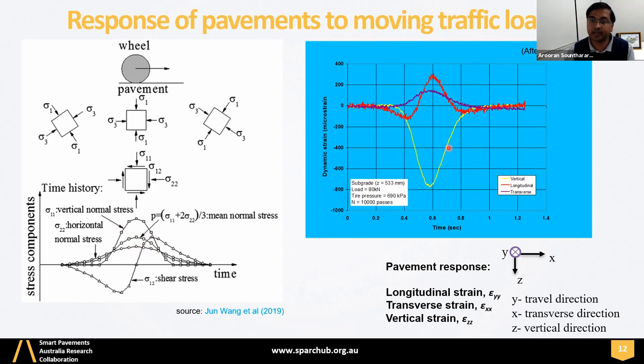This is a real measurement in the field when the vehicle moves. So you see the time here. The vehicle movement is captured with time, right? So time versus stress or strain here indicates the vehicle moves at a certain speed in a certain direction. So what happens to the strain at this location? Z equals 533, that means from the surface we are measuring the strain at a depth of 533 millimeters. It's about half a meter. And the applied load is about 80 kilonewton, and the surface contact stress, estimated, is about 690 kilopascal, right?